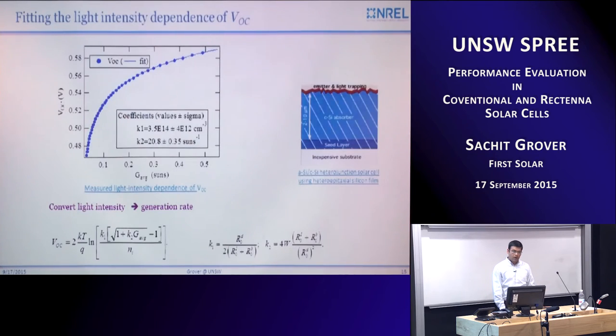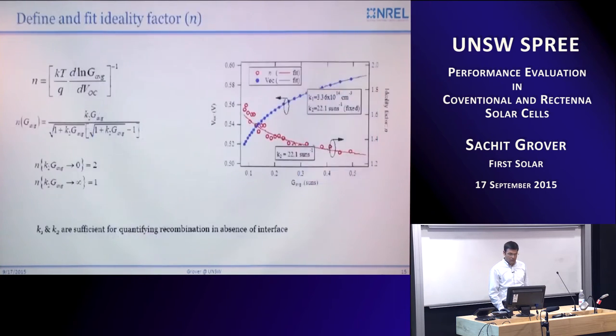So I use that to fit the light intensity dependence of VOC for one of these amorphous silicon crystalline silicon heterojunction devices, and get a really good fit there. What you can also do is define an ideality factor with it, where the ideality depends on the light intensity derivative of the VOC. And here in red is the ideality factor. As the light intensity increases, the ideality factor goes from approaching 2 to approaching 1 at high intensity. And that's the transition going from space charge limited to quasi-neutral limited or interface limited recombination. And again, there's a reasonable fit and agreement between the fit quantities, the numbers there.